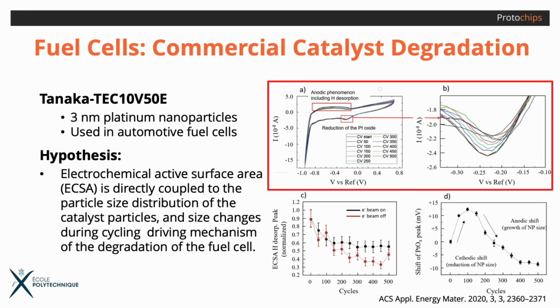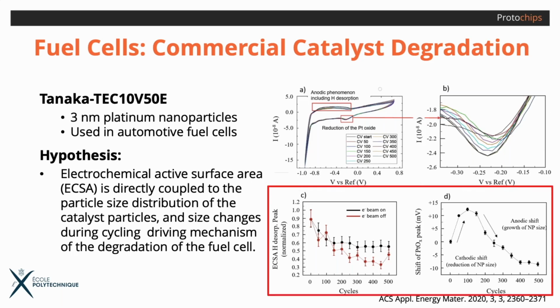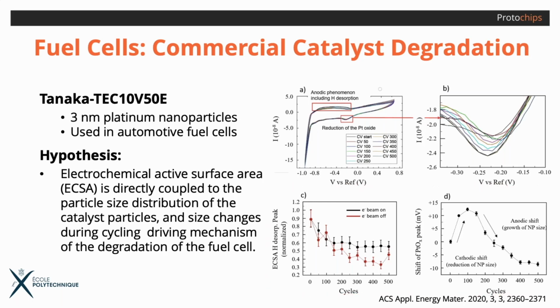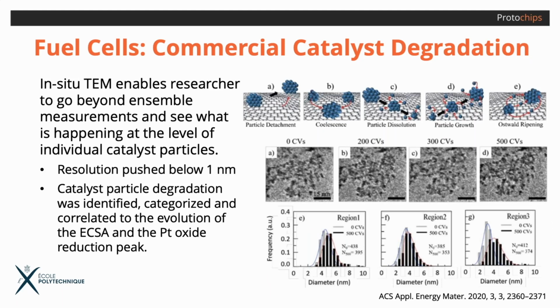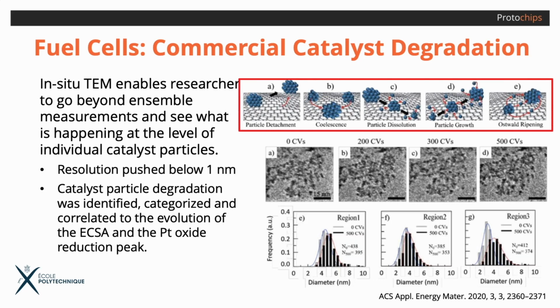Cyclic voltammetry experiments were performed in situ up to 500 cycles to replicate normal stress testing protocols. The platinum oxide reduction peak underwent a cathodic shift after the first 100 cycles, followed by an anodic shift. This indicated that the nanocatalyst underwent a reduction in size, followed by subsequent growth. Using energy filtering techniques, the researchers were able to push the TEM resolution in liquid below 1 nanometer, enabling them to follow the different types of degradation processes hinted at in the electrochemical data. These include detachment, coalescence, dissolution, growth, and Ostwald ripening.